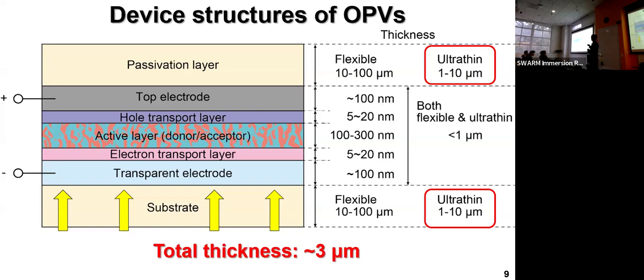But if we replace the opaque electrode with a transparent electrode as the top, then we could make semi-transparent OPV systems. Then important layers besides these 5 functional layers are the substrate and the passivation layer or superstrate. Normally, flexible organic solar cell researchers use a 100 micron thick polymer substrate, such as 100 micron thick PET substrate, PEN substrate, or transparent polyimide substrate. But we are using a 1 micron thick substrate and a 1 micron thick passivation layer to make the total thickness around 3 to 4 micrometers.